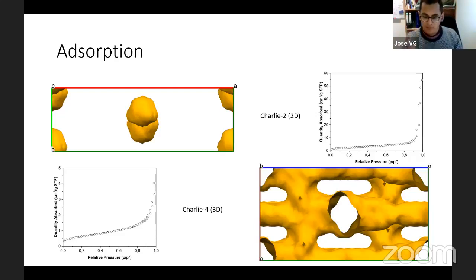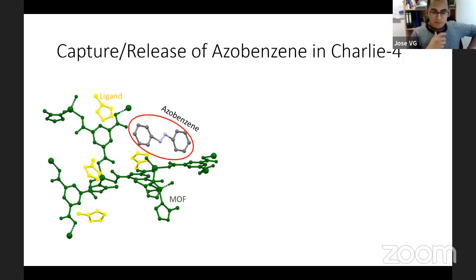However, I came up with the idea to introduce some guest molecule during the synthesis of Charlie 4 and practically trap that material inside. As an initial molecule, I tried azobenzene. And as you can see, we can trap azobenzene inside of the material. Here you can see the azobenzene in the red circle, and you can see in yellow the trapped 2-methylimidazole, which blockades the pore. But the surprising part is you can see the azobenzene. So practically you can have the structure of some trapped molecules inside of the material.